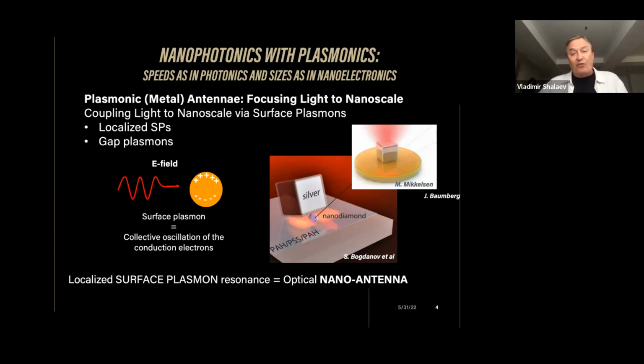There are all types of ways to excite these plasmon modes. And if you would like to accomplish the highest possible confinement, in the case of the sphere, the confinement will be dictated by the size of the sphere, which could be, let's say, 10, 20 nanometers. But if you go towards so-called gap plasmons, in this case, you have a dielectric gap between two metallic structures supporting this free electron oscillation. Then such gaps could be exceptionally small, a few nanometers, 1 nanometer. And that actually enables record-breaking confinement of electromagnetic modes. And that's the thing which I'm going to use to speed up quantum processes.